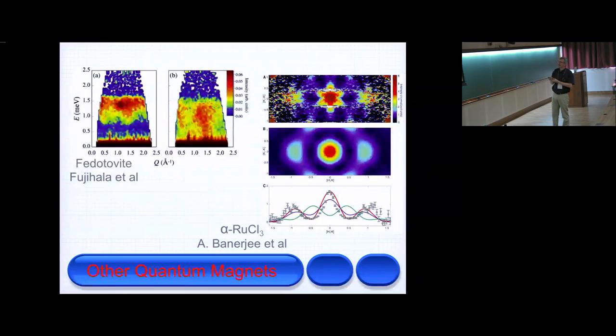So here's a chain system where, in the ground states, there's no Bragg peaks to look at for the magnetic system, but they can get lots of nice inelastic neutron scattering. And the idea is now to model this to understand what kind of linear chain system they have. And here's the trichloride, where this is the data. They see wonderful excitation spectrums. This is at some given energy. I think it was something like 5 meV. They have a pattern that looks like so.